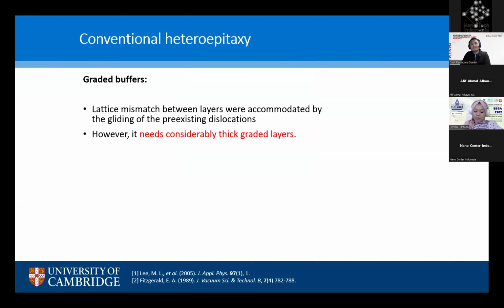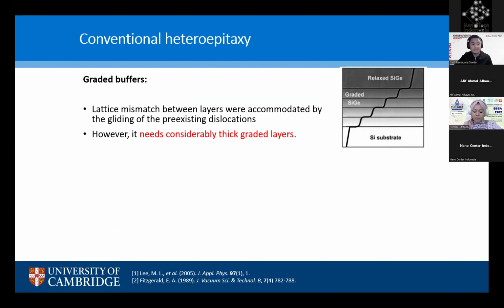So as I mentioned earlier, the first one is obviously you try to grade your materials, so graded buffers. In the graded buffers, the idea is that lattice mismatch between layers is accommodated by the gliding of the pre-existing dislocations. So what I meant to say is if you try to grow a relaxed silicon germanium alloy, you try to grade the composition of germanium before you reach your desired alloy composition. So you increase slowly so that the existing misfit glides, then becomes misfit and glides again, and so on and so on.